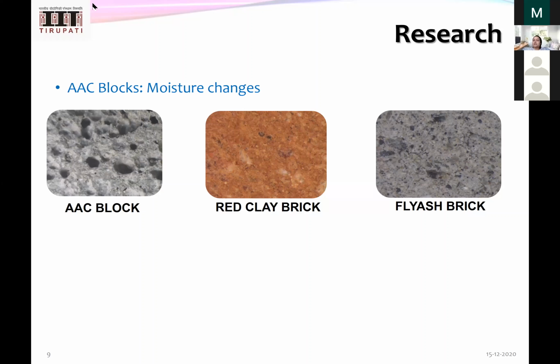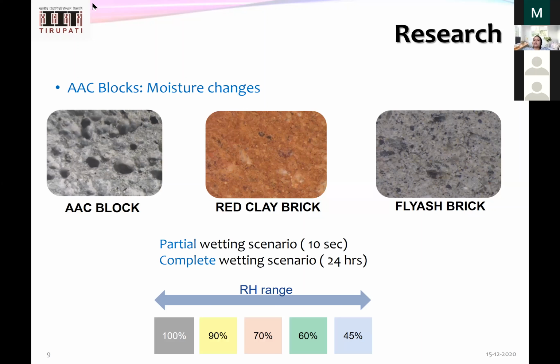Then we tested this material in two different scenarios. One scenario is partial wetting, which all of us who know at least minimum construction are familiar with. We wet the brick before using it. So we do a partial wetting. We just dip it and take it out. Then a complete wetting, where we keep it inside the water for 24 hours. There are options possible in between also. A lot of options are there in between. We could choose one hour, 6 hours, 3 hours. There are different options, but at least two options I'm explaining here.